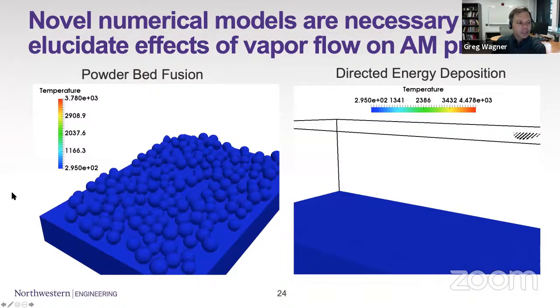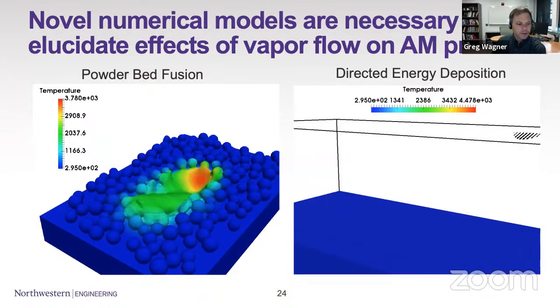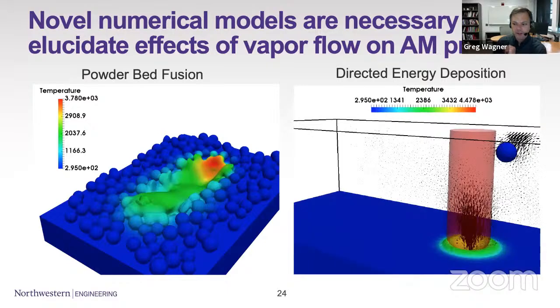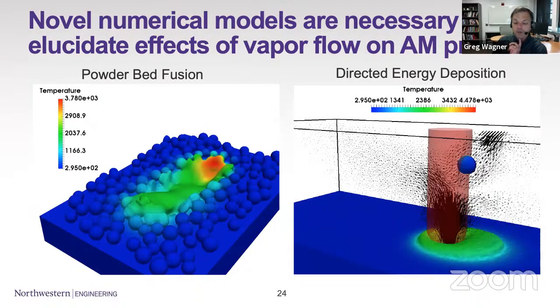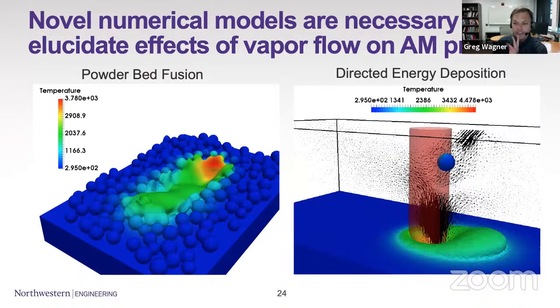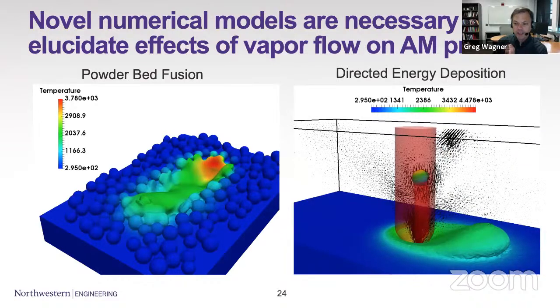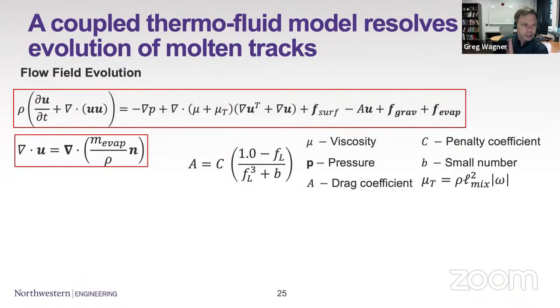So we've developed models and multi-phase simulation techniques that allow us to simulate this sort of moving interface with evaporation problem, both at the powder bed scale for powder bed fusion problems and for DED problems, where we can look at the injection of powder particles and their interaction with the laser and with the melt pool. I'm going to spend a few minutes on the formulation for that and some of the results.